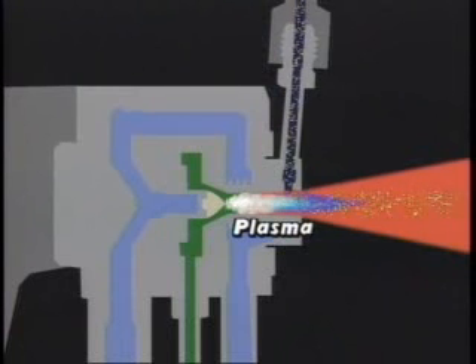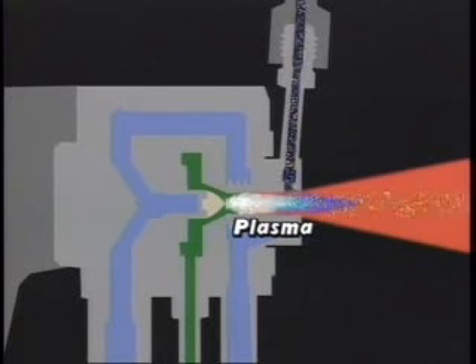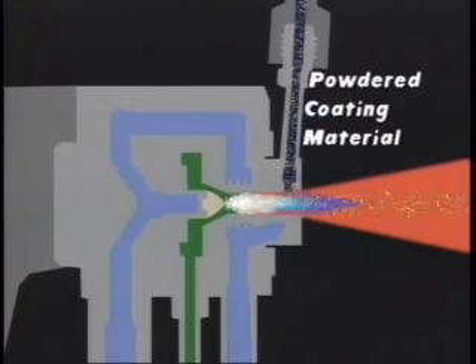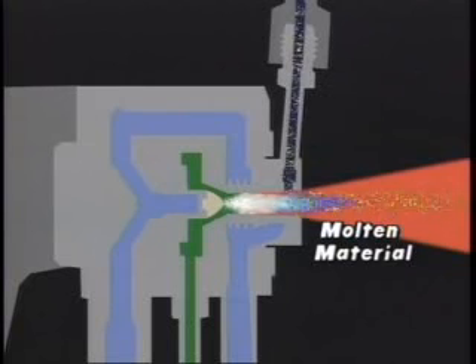During plasma spraying, a powerful electric arc excites gas molecules, producing an extremely hot ionized gas called plasma, which reaches controlled temperatures from 5,000 to 30,000 degrees Fahrenheit, depending on the application. The powdered coating material is then injected into the high-velocity plasma stream. This transforms the coating material into a molten or plastic state, while the inert environment prevents adverse reactions that would otherwise result from the extreme temperature.